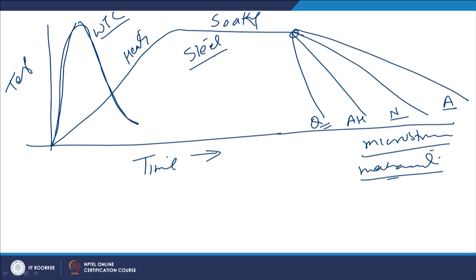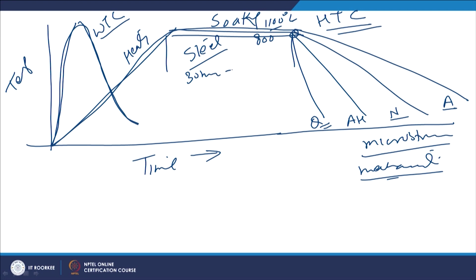So, if we compare the weld thermal cycle with the typical heat treatment cycle, then heat treatment cycle is very long, where it takes very long to heat to the required temperature, which is normally in the range of 800 to 1100 degrees centigrade, and then followed by the soaking for longer period, which may vary as per the section size from say 30 minutes to 2 to 3 hours, and then different cooling rates, varying from 2 to 5 degree centigrade per second to 100 to 200 degree centigrade per second.